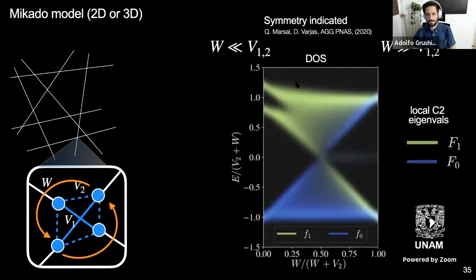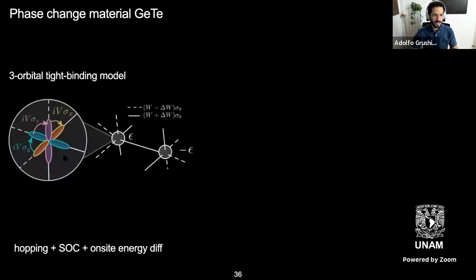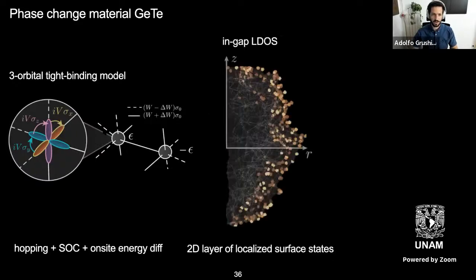So indeed, in this paper, we showed that not only this model, but any model that has threefold or fourfold or any fixed coordination, and in any dimensions, you can symmetry label. And this allows us to predict very efficiently topological phases in amorphous systems. And so we went a little bit further in 3D, and we cooked up a model for germanium and tellurium, which is a little bit more complicated, and found that indeed there's a phase where, when the average Peierls distortion dominates, you have some shell of localized states at the surface of the 3D system. If you make a blob, and you cut this blob, you'll see that there are eigenstates at the surface.